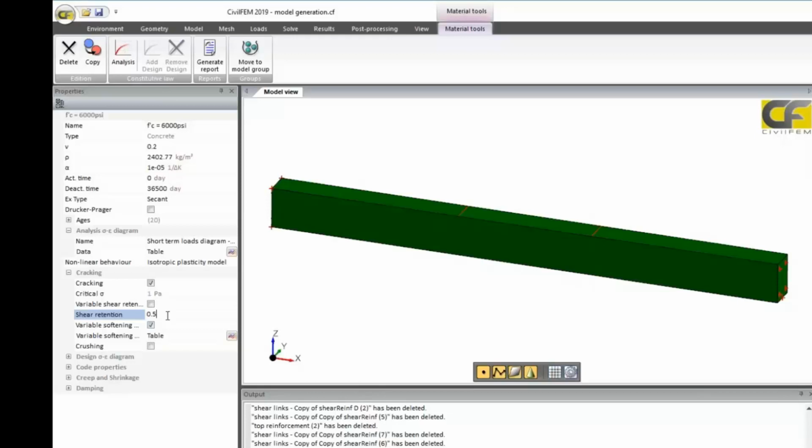In those elements, after cracking, the shear stiffness will be multiplied by this value. So in this case, I said 0.5, it will mean it will have half of the original shear stiffness before cracking. Well, it's a high value, and this could be good for models with small cracks and with a lot of reinforcement